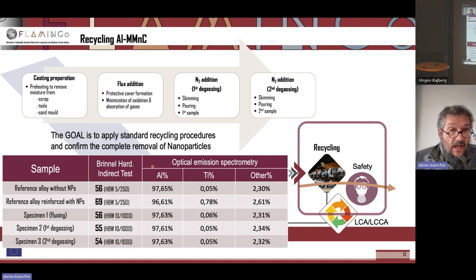And as we can see already from the first fluxing with nitrogen addition, these were basically going back to the original state without nanoparticles, further confirming that this approach is quite usable as a strengthening mechanism in the current uses of aluminums.